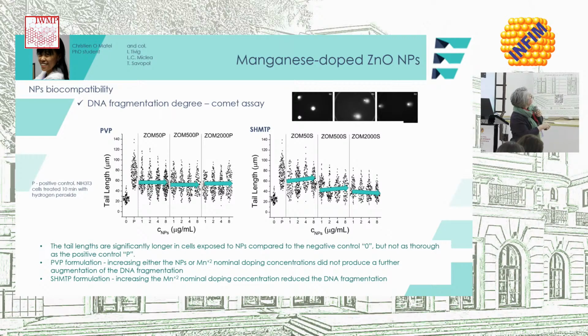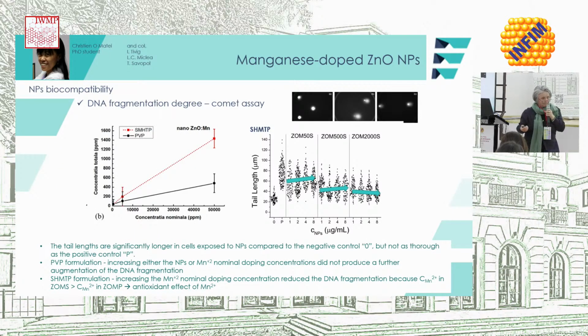And we saw that in the PVP formulation, increasing either the nanoparticle concentration or the manganese doping did not produce a further augmentation of the DNA fragmentation. In the case of the SHMTP formulation, this increase of the manganese nominal doping concentration reduced a little bit the DNA fragmentation. And this can be correlated with the fact that in the SHMTP type of nanoparticle, there is an increased doping in manganese, and the manganese itself has an antioxidant effect.